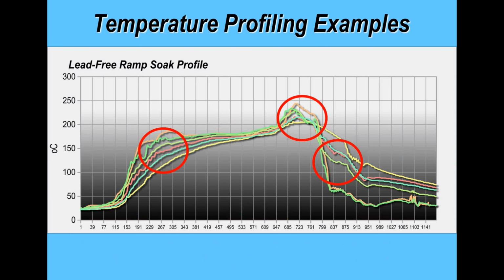So we're seeing, as we heat up the board assembly, a variation of temperature. As we go into the reflow zone, we're seeing a variation in temperature, and as we cool the product down, again you can see this variation. And what we're trying to do is minimize that variation. By minimizing the variation, what we can do is hopefully either speed up the process, or we can minimize the peak temperature, which is what we're always trying to do in a reflow soldering process, because temperature has an impact potentially on the components and the final quality of those.